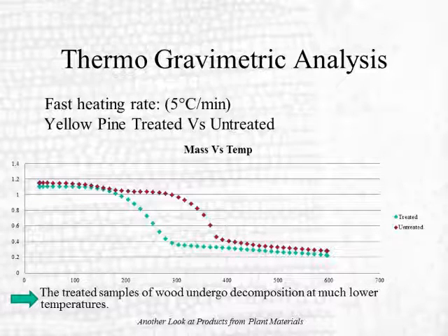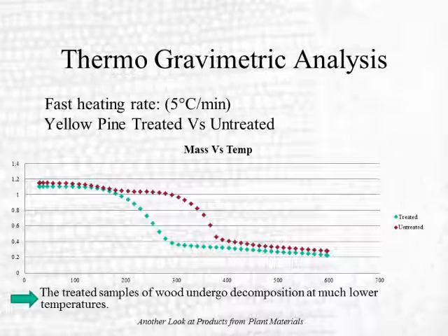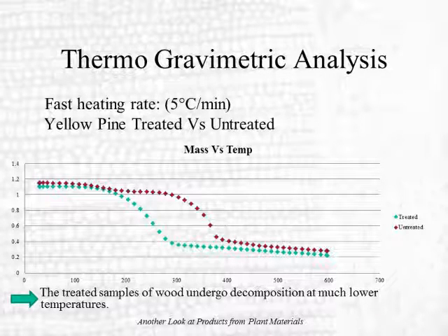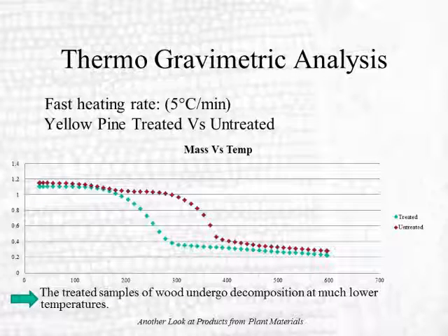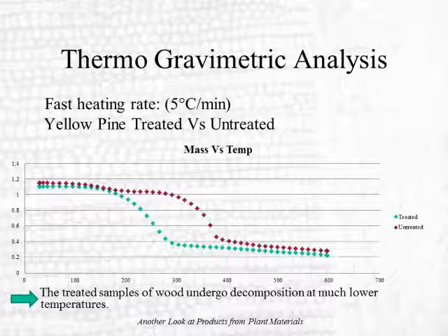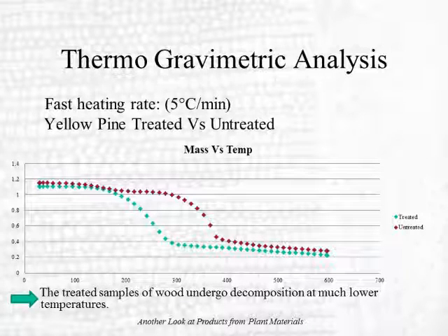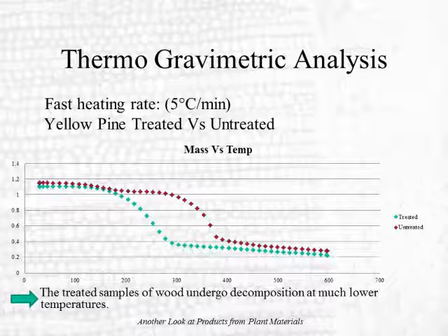The other aspect that comes from this is some TGA work. If you look at the mass versus temperature of treated versus untreated yellow pine, then what you find is the untreated wood decomposes, roughly after moisture is driven off, mostly between 275 and 400 or 450 degrees centigrade. The greatest drop-off is somewhere around 350 degrees. Whereas the treated wood begins its decomposition at significantly lower temperatures when measured in this way.